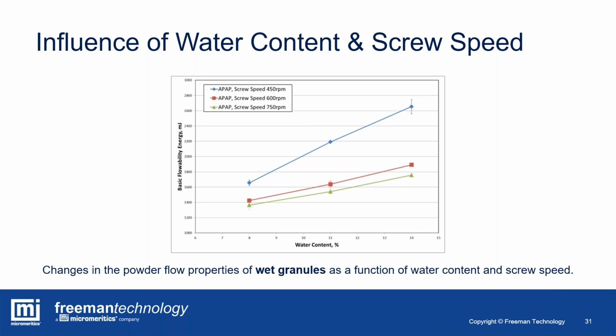You can see the lowest screw speed at 450 RPM gives us this blue data set, and therefore substantially stronger and bigger granules at these lower shear rates, which is perhaps counterintuitive, but it allows more time for the particles to shear and for the fluids to disseminate or distribute through the sample, and for larger and stronger granules to form.